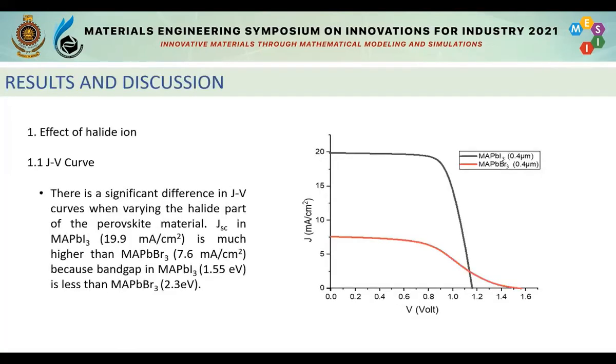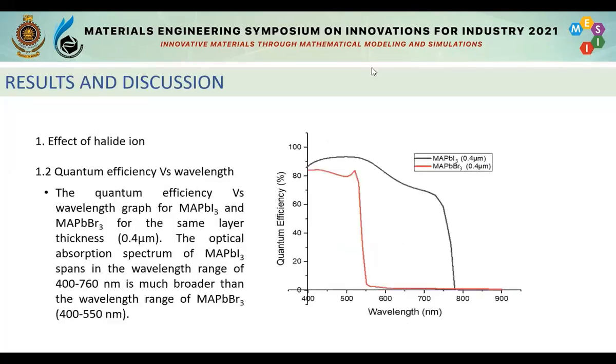Here are the results and discussion of our research work. When considering the effect of halide ion, there is a significant difference between IV curves when varying the halide part of the perovskite material. The short circuit current in methyl ammonium lead iodide is much higher than methyl ammonium lead bromide because the band gap of methyl ammonium lead iodide is less than methyl ammonium lead bromide.